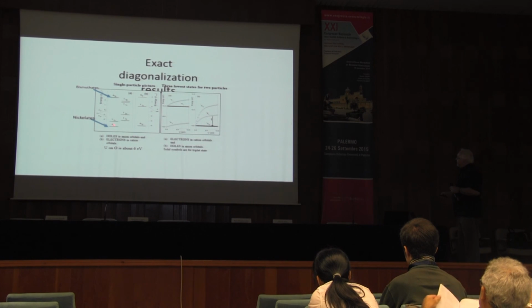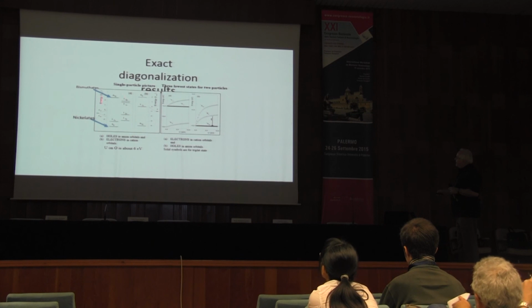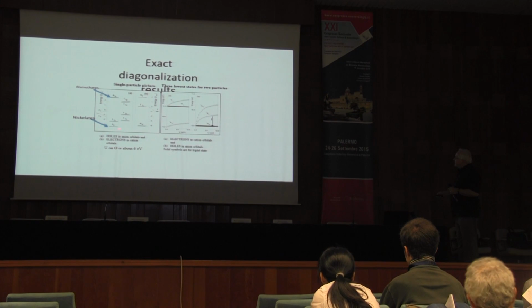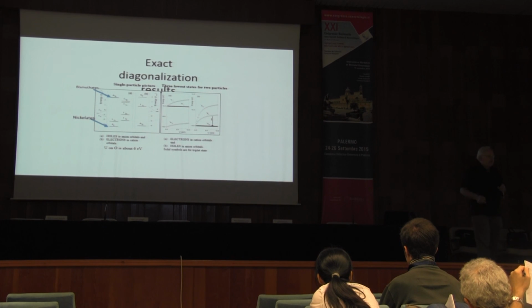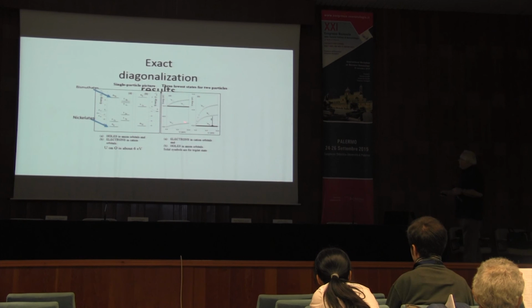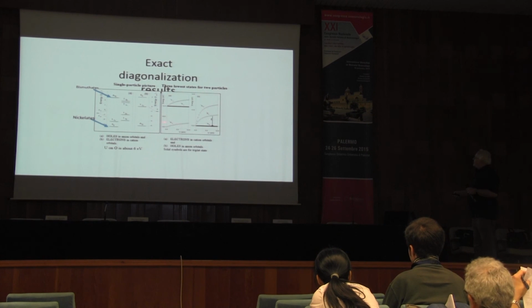But if I take and put two holes into this octahedron, then I have the possibility of forming a triplet, because the lowest energy state was an EG state, so I can have one hole in x squared minus y squared and the other hole in 3z squared minus r squared. And it could form a triplet. And look at what happens if you do an exact diagonalization.